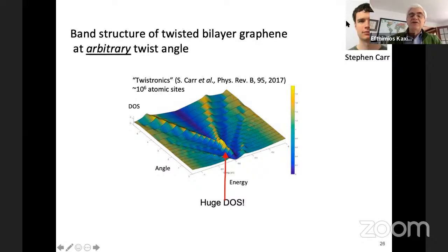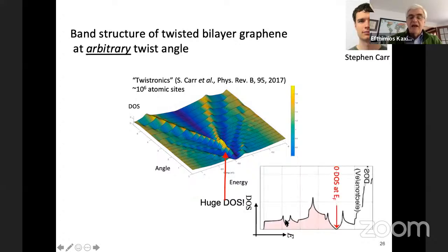And another student, a very good student that I worked with, Stephen Carr, produced this plot. So this is now a plot of the density of states on the vertical axis as a function of the energy on this axis and as a function of the twist angle on this axis. And then you see that at zero twist, you have this density of states of graphene. Let me reproduce this. This is the plot that I showed you again, but now flipped over to correspond to this plot. So this line here is the same as the crosscut of this, but blown up. And you see here the zero density of states, again, zero density of states at the Fermi level.